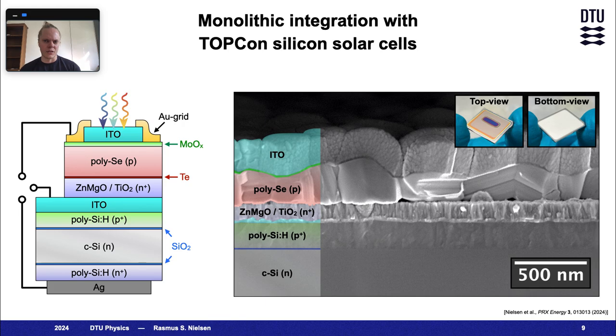Here, I'd like to highlight that both of our ohmic contacts needed to be replaced by a transparent conductive oxide, and in this case, that is ITO, and that the polarity of the top cell has changed. Our single junctions were fabricated in a superstrate configuration, where one would just shine light through the substrate, but of course that's not possible when you're doing it on silicon.